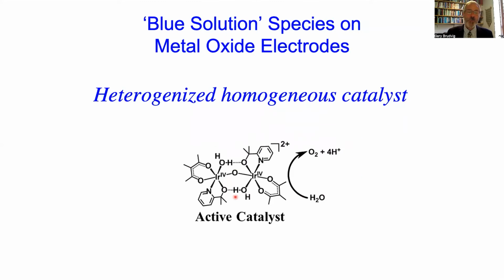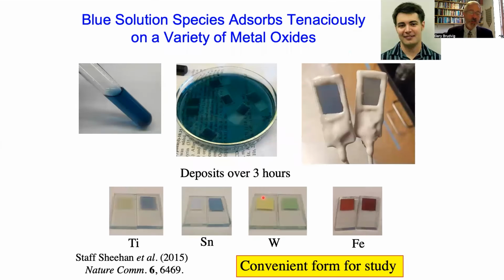So now we'd like to put it on a surface, or heterogenize it, by attaching it to a metal oxide surface. And this is actually quite easy to do for this complex because it spontaneously adsorbs to metal oxides. So here's a sample of our blue solution. This is the dinuclear iridium complex. We can soak a mesoporous metal oxide film in this solution, and it will spontaneously adsorb on the surface. So titanium oxide, tin oxide, tungsten oxide, and iron oxide.